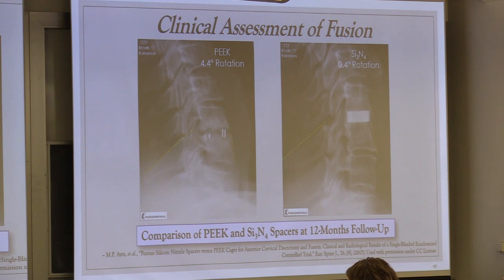But this is a case that shows one particular implant of PEEK and silicon nitride. There's a couple of things that are quite obvious. These are flexion extension radiographs. So you can see that there's basically no movement around the silicon nitride, meaning that the fusion has actually taken hold very well, and it's holding the two vertebrae together quite nicely. And you can also see the outline of the implant and a little bit through the implant. So it has this radiolucent behavior as well.